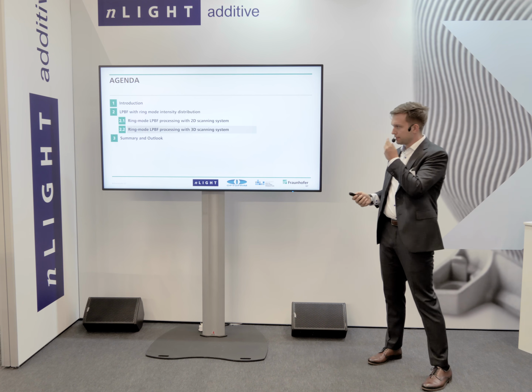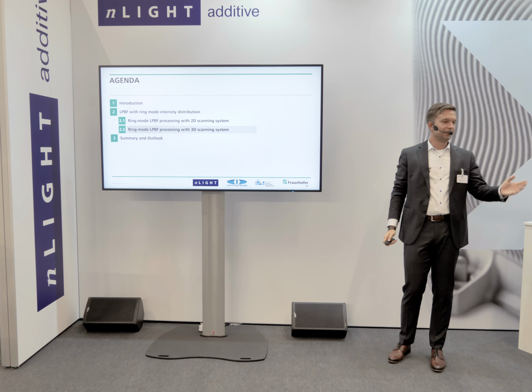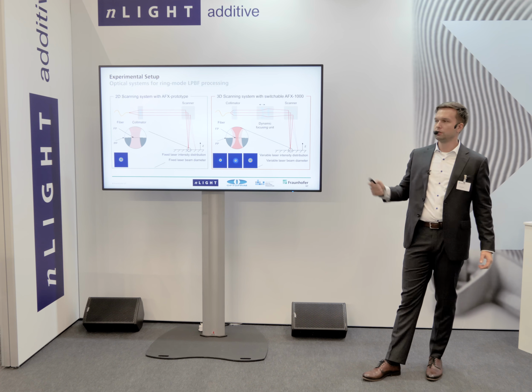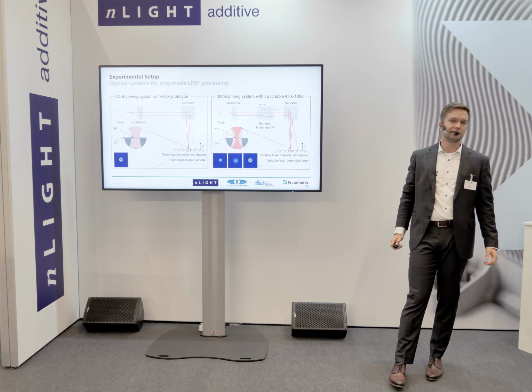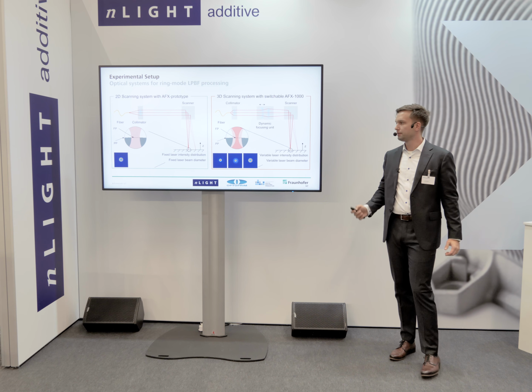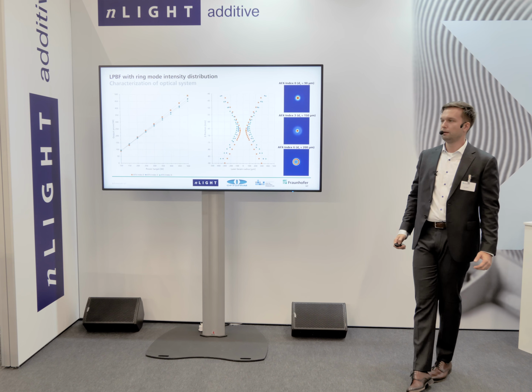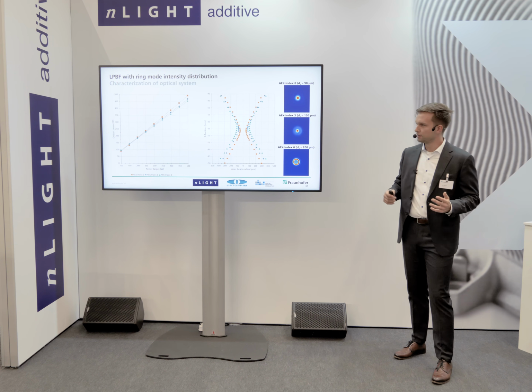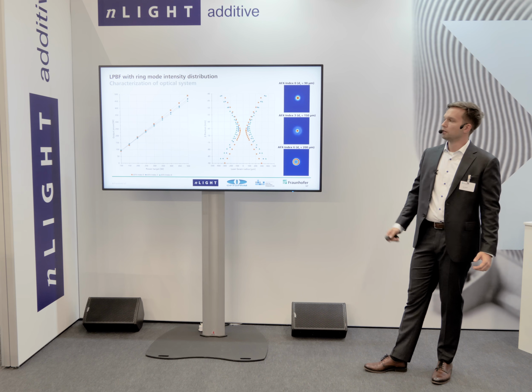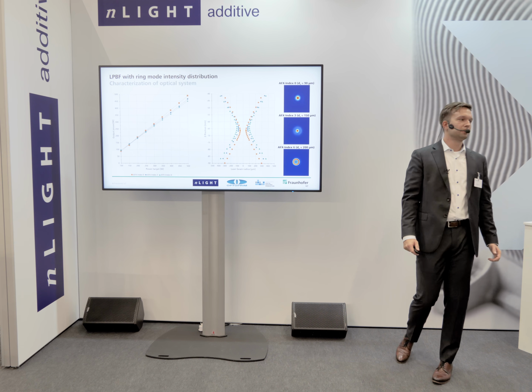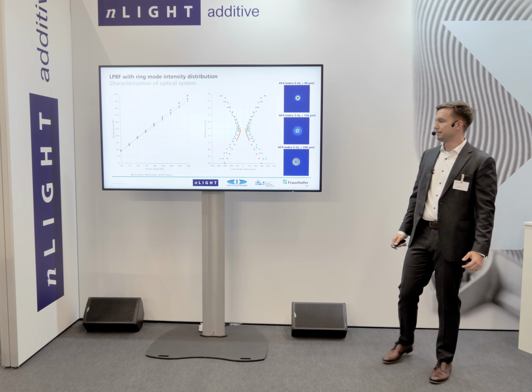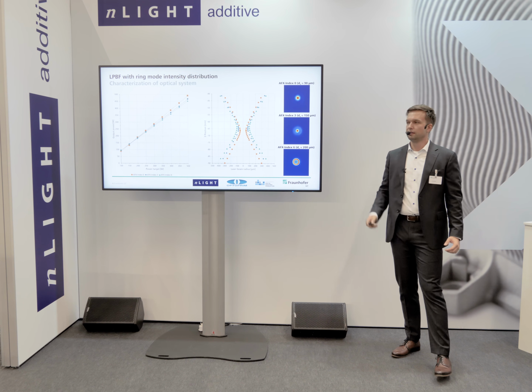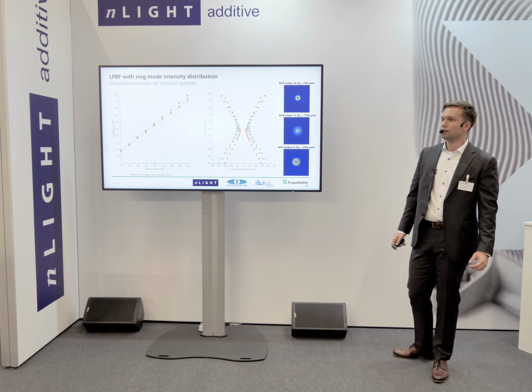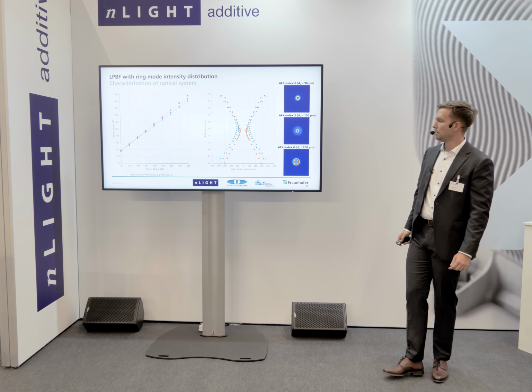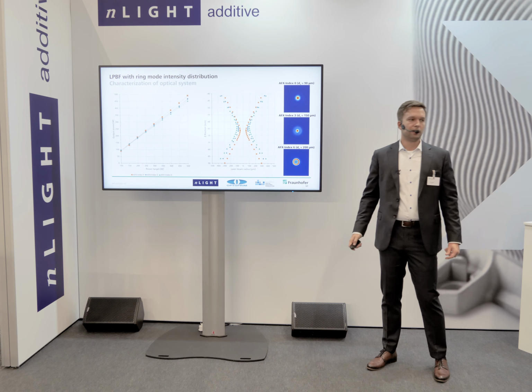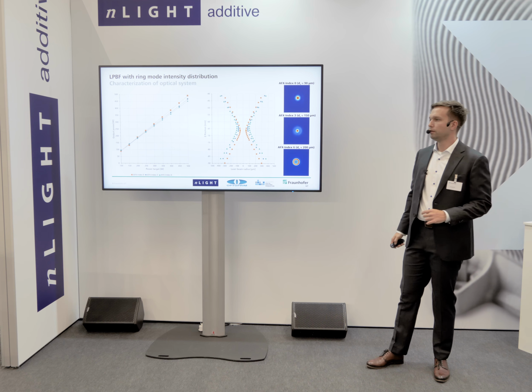Which now brings us to the results that we obtained with the final AFX product. So as I mentioned, we coupled it with one of our 3D scanning systems, as it is in most L-PBF machines. We measured the system to see if it yields the properties that we calculated, so caustic and laser characteristics measurement for index 0, 3, and 6. And we found that the resulting beam diameters corresponded very well to our calculations, and we found also that the focal planes actually align very well.